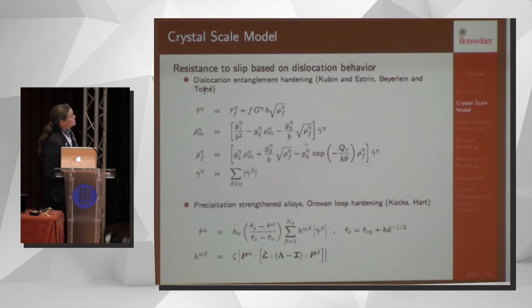So I'm going to give just examples. These are some typical types of constitutive models that we've been using for modeling the mobile and immobile dislocations, or the hardening, if you like, in our work. But there are many, many models out there with different levels of complexity. I would say this is maybe a medium to low level of complexity. We're doing some homogenization. We're not considering all the details of the dislocation types and every possible interaction, but we're kind of averaging it out using some sort of phenomenological ideas. So for dislocation entanglement hardening, this work is based on classic work of Kubin and Estrin, and more recently by Beyerlein and Tomé on hexagonal materials.